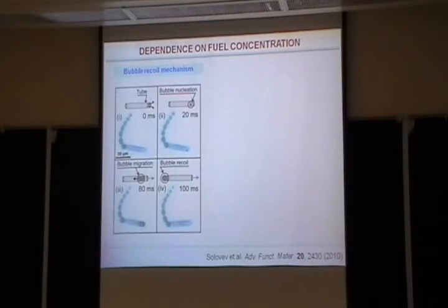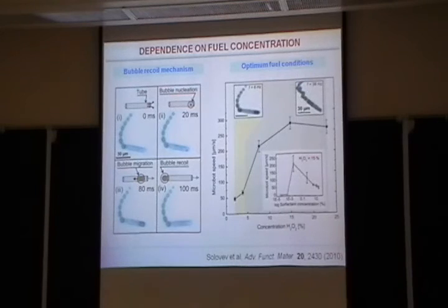And so this is the mechanism that suggests where the hydrogen peroxide enters, oxygen is being formed, and the bubbles are expelled from the other side, the wider side. And just like ours, there's a saturation, which is catalysis limited, so just upping the hydrogen peroxide concentration doesn't necessarily speed up these things. You reach a limit.